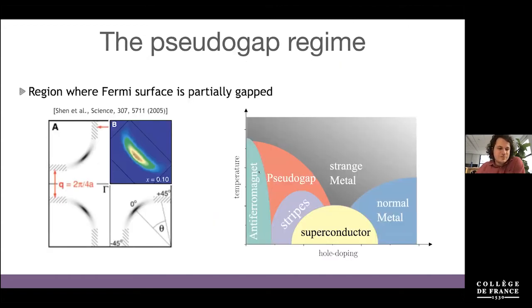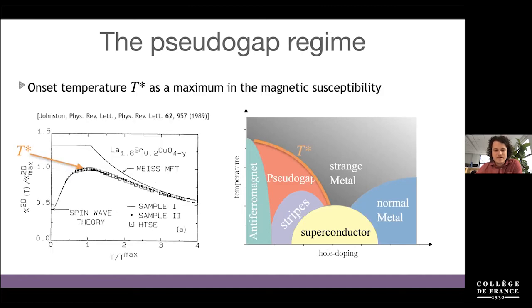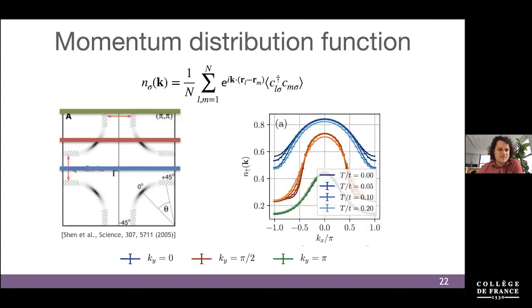So let's recap this a little bit. The pseudogap regime in the cuprates is characterized by the Fermi surface being gapped out at the boundary of the Brillouin zone, with gapless modes close to the nodal point. One finding is that whenever this occurs, there's a maximum in the magnetic susceptibility. So there's this T star, which characterizes the onset of the pseudogap phase. This is the first indication that something similar might be happening in the Hubbard model, since we see this maximum in the magnetic susceptibility.